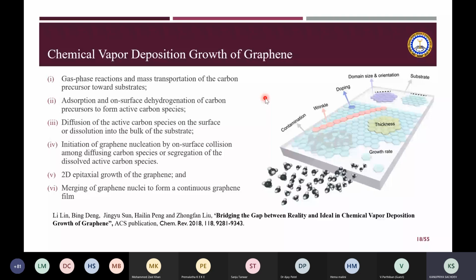These are the important things. The mass transportation of the carbon precursor towards the substrate. And then these carbon precursors have to be adsorbed to form active carbon species. These active carbon species have to diffuse, and their dissolution into the bulk of the substrate has to take place. And then there is the initiation of the graphene nucleation by the on-surface collision among these diffusing carbon species or the segregation of the dissolved active carbon species. And that leads to the two-dimensional epitaxial growth of the graphene, where the graphene nuclei then merge to form a continuous graphene film.